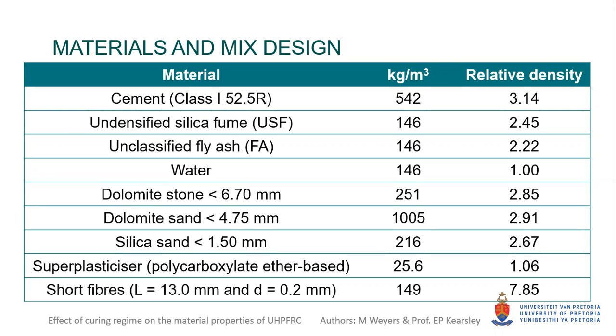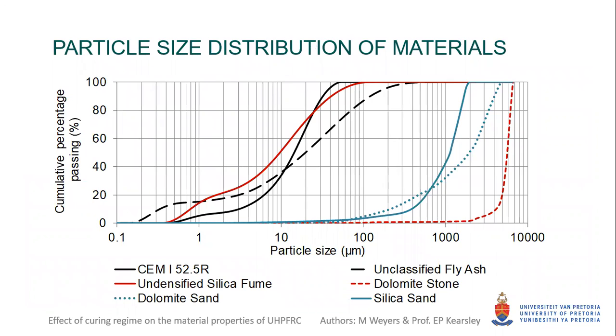Three types of aggregate with different grain sizes were chosen to enhance the packing density, namely silica sand, dolomite sand, and crushed dolomite stone. Superplasticizer was added to improve the workability of the mixes. Straight steel fibers with a length of 13 mm and a diameter of 0.2 mm were used in all the mix designs. The particle size distribution of all the dry materials for the mixture can be seen in this figure.